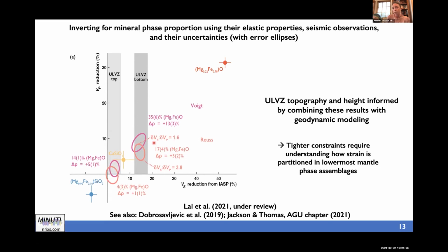And this figure shows that the proportion of these phases, be it for magnesiowüstite or any other region in the earth, if one is doing this inversion, depends, of course, on how the strain is essentially partitioned amongst these grains. What we show is a Voigt bound and a Reuss bound, but you can see that the actual proportion, the final constraint, comes from understanding how strain is partitioned into these phases, which I know is an ongoing problem to be understood and solved. And so certainly more understanding in that area would lead to tighter constraints of not just this area of the earth, the core mantle boundary or D double prime, but other areas in the earth.